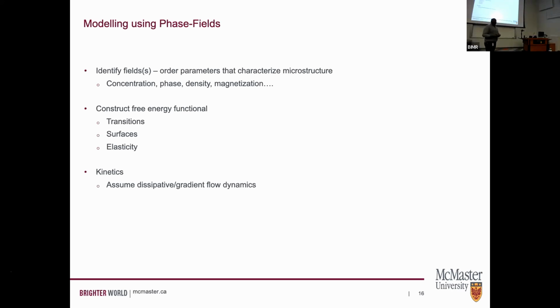The next thing you do is you try to construct a free energy. We're all scientists. We can't violate certain laws. One of them is energy. And so you construct this free energy in such a way that you account for things like, am I having to go through a phase transition during this transformation? Do I need to worry about elasticity? Do I need to worry about surfaces? So once you do that, you construct this free energy functional with the caveat that whatever dynamics you choose to solve, or kinetic equation you choose to solve, this free energy is always minimizing energy or it's maximizing entropy.